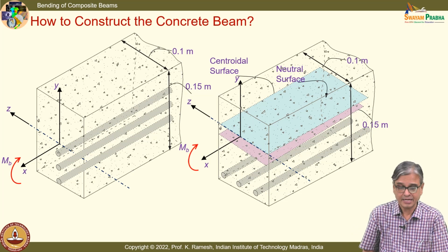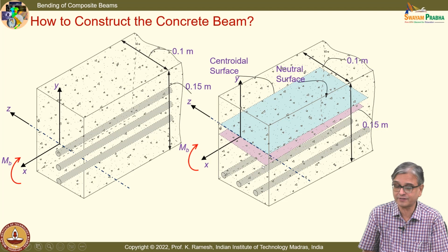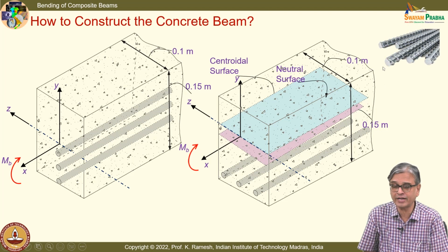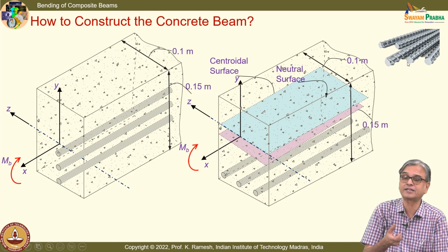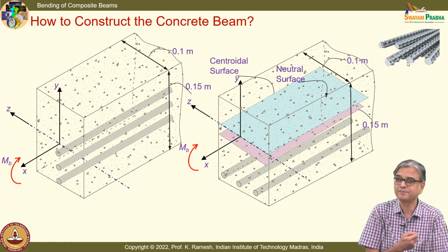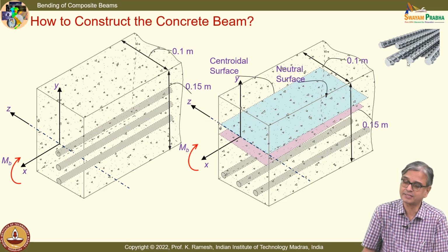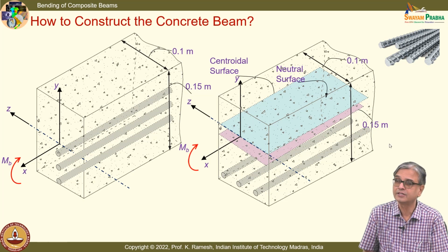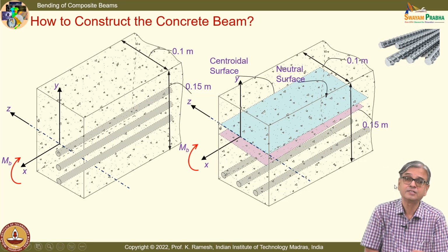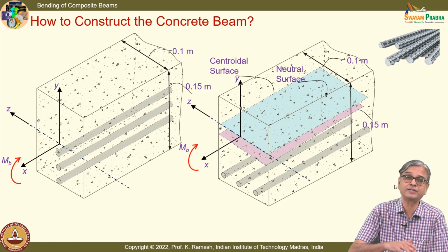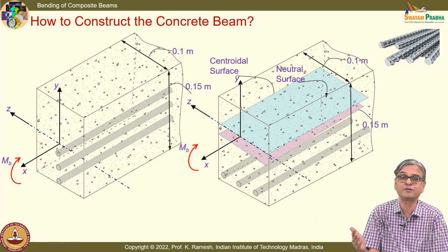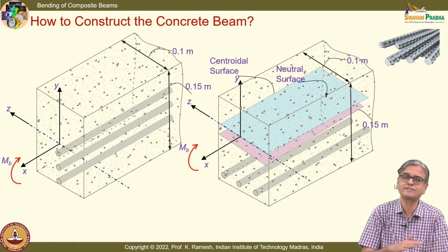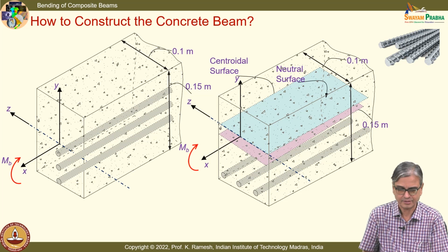Fine. So, I have to find out where the neutral surface is, and to ensure that I have good bonding, the rods are not perfectly cylindrical; they have these projections so that they cannot come out easily. And people also put some kind of a polymer coating so that it does not corrode. The challenge is the polymer should bond with steel as well as it should bond with concrete. All these are field challenges. Okay.